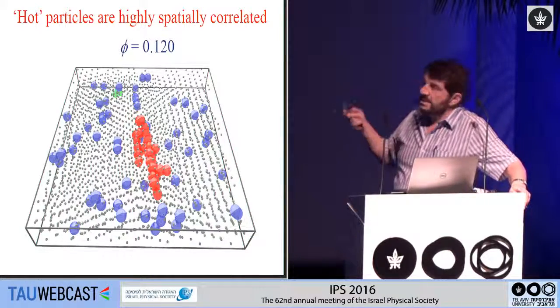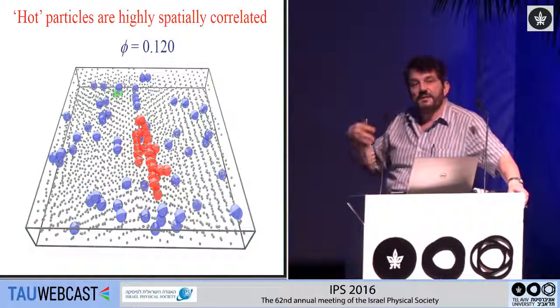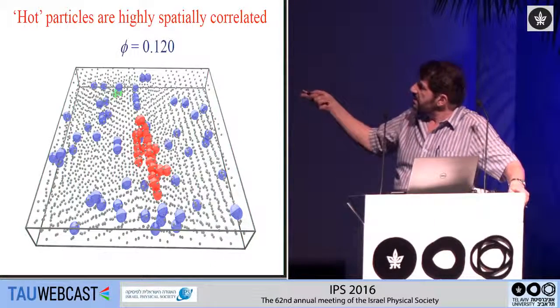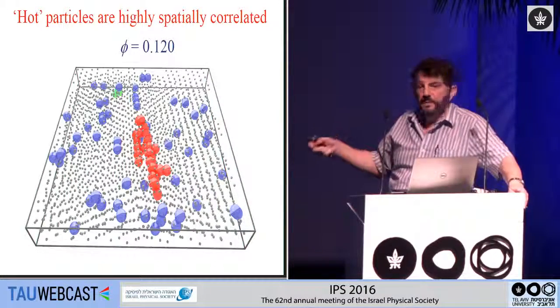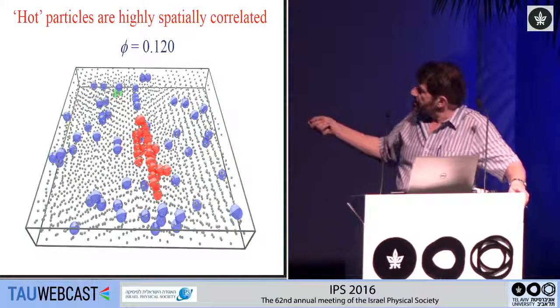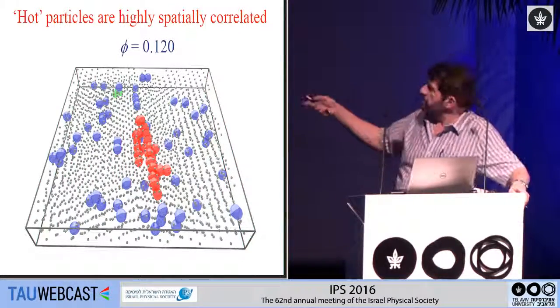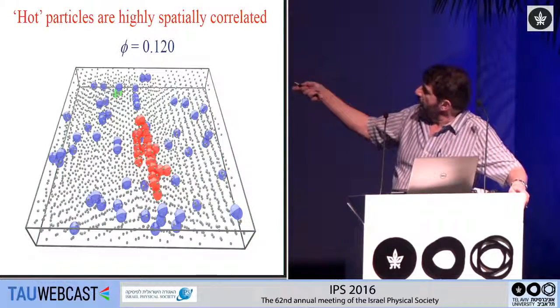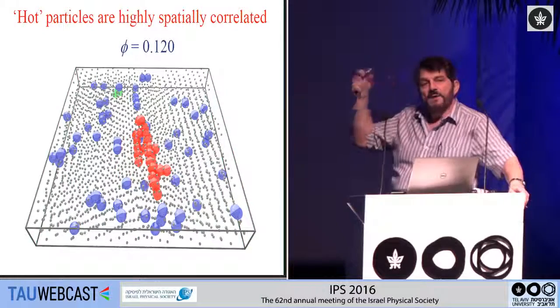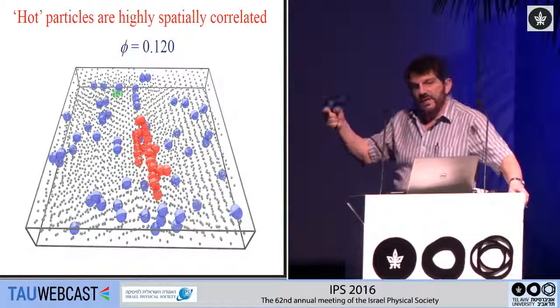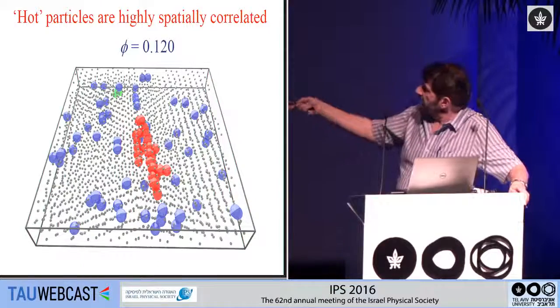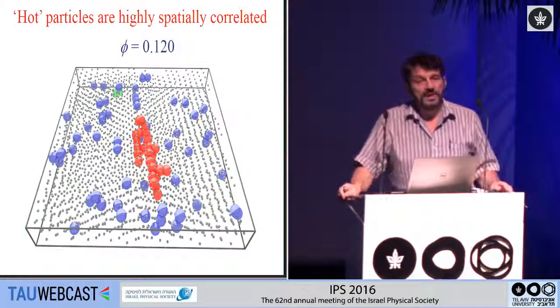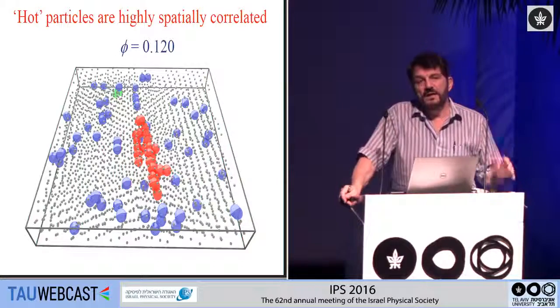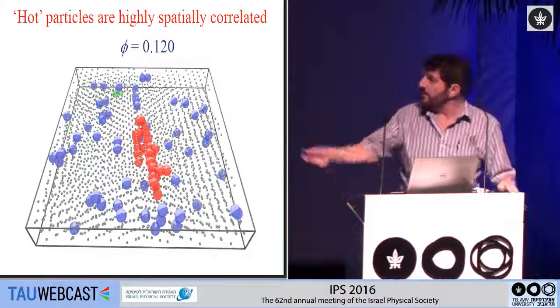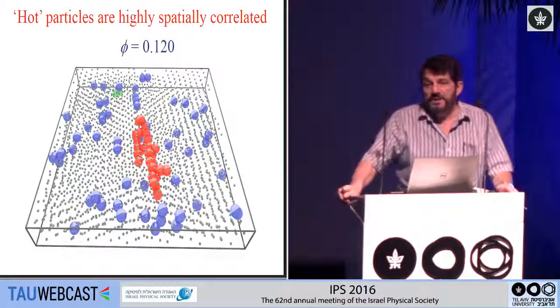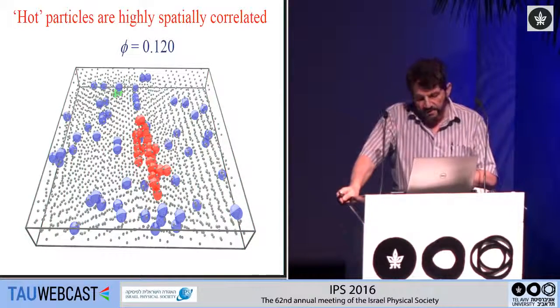And this is looking at a system that's well away from the melting, a very solid-like system. Nevertheless, you can see some superheated particles. And what's interesting is that there's relatively strong spatial correlation. In fact, when I draw these particles in red, these are particles that are joined as nearest neighbors. They're all superheated, and you can see that they form this relatively large cluster in the midst of a random system where there are only a few small clusters and a much smaller number of superheated particles.